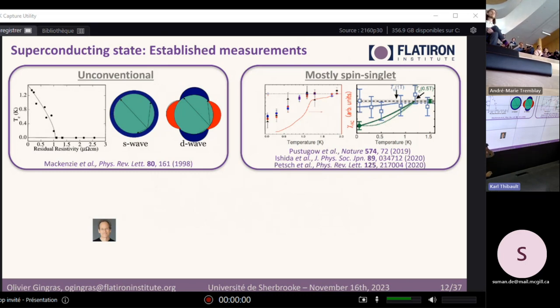So this has been a very long discussion for strontium ruthenate. Actually, the same experiments for 25 years were pointing toward the opposite conclusion, which is that it was spin triplet. The reason is that here we're looking at the magnetic susceptibility in the presence of a small field. When you go into the superconducting state, if the pairs are singlet, they cannot align with the field and they will reduce the spin susceptibility, while in the triplet they can maybe align. So in a triplet state you would expect it to be constant if you're in the right direction, and in a singlet state you would expect it to be decreasing.